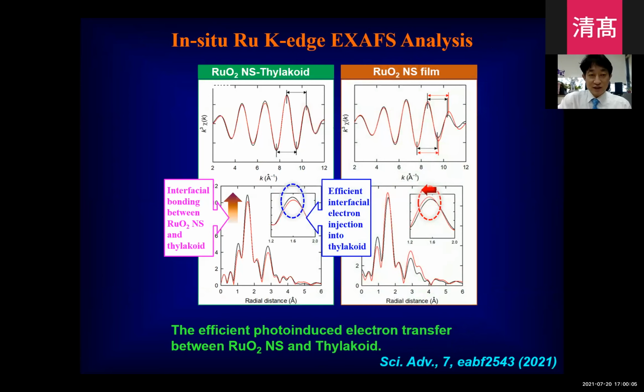Also, we did in situ XAS analysis. In the case of bare ruthenium oxide, we also observed a shift of the FT peak position due to charge accumulation of ruthenium oxide. But in the case of the ruthenium oxide thylakoid hybrid system, we didn't observe a significant change of the FT peak position. This is the evidence for efficient interfacial electron injection from ruthenium oxide to the thylakoid.